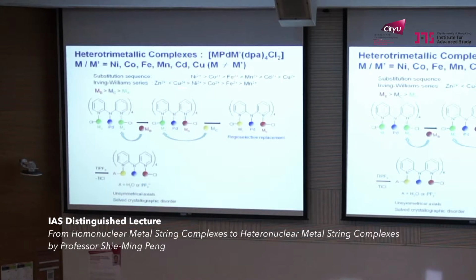But copper 2, actually, this is not copper 2. We substitute the metal at high temperature. Not only high temperature, but at that temperature, more than 100 degrees, copper 2 is easily reduced to copper 1 and becomes labile. So I can say it's consistent with the Irving-Williams series.